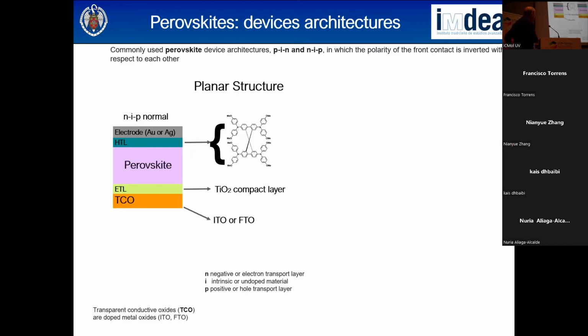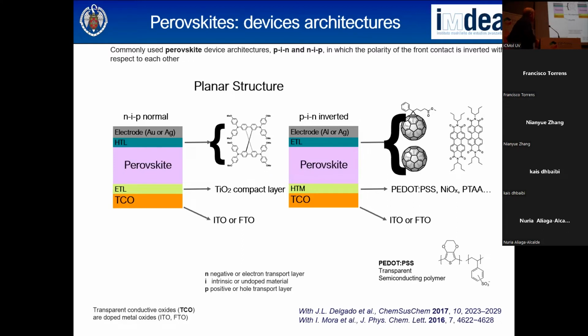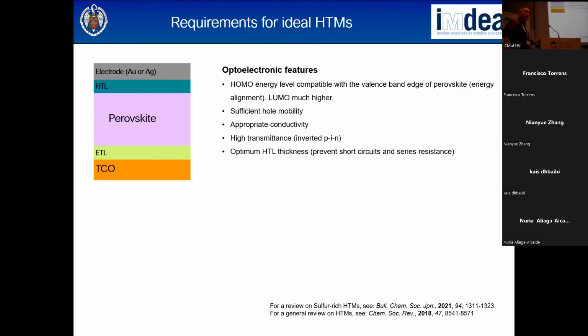So if you have the so-called inverted device, then the electrodes are moved. Now the electrode is different, usually aluminum or silver. We have also addressed this kind of device in collaboration with Juan Luis Delgado and Ivan Mora, for instance, just to give you a couple of papers on this one, because we develop fullerene chemistry as well. So let's go already to the hole transporting materials or layers. If you need this layer here, it has to fulfill some optoelectronic properties. Among them, the HOMO energy level should be aligned with the valence band of the perovskite, as I will show you later on.